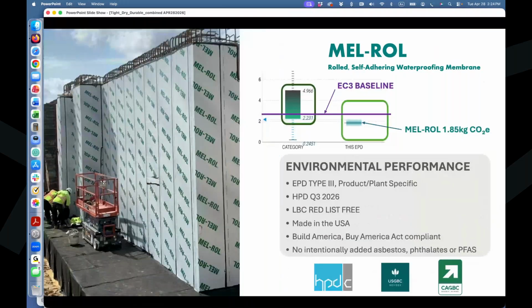So in considering Mel-Rol and its EPD, we're going to look at the snapshot from the EC3 tool, which is in the center of the slide. The dark green box on the left shows the kilograms of CO2 emission range for EPDs in this category, which range on the low end, if you really squint your eyes a little bit, you can see it's about 2.2 to a high of around 5. The light green box on the right shows Mel-Rol at 1.85, which is below the purple EC3 baseline and below all the other EPDs in this category of materials. So, outstanding carbon story with that product.